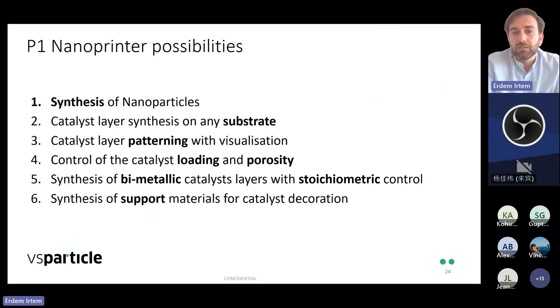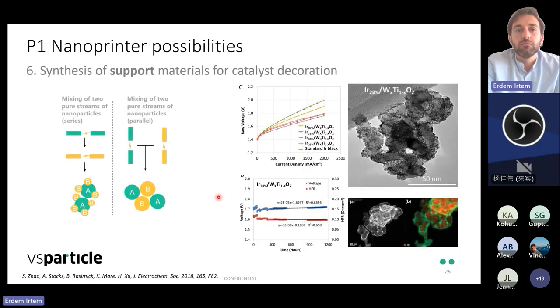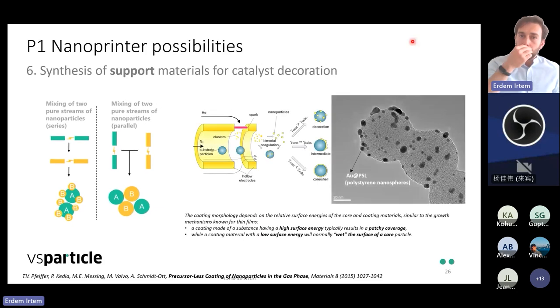So synthesis of support materials is also possible, which has been conducted before as well. Just to give you an example from PEM water electrolysis, I like this article from a few years ago where they have shown that tungsten doped titanium dioxide decorated with iridium was quite stable for over 1,000 hours. And when I was looking at the previous publications with the VSParticle generator, one of them, almost a decade ago, showed that it is possible to decorate, for example, gold on polystyrene nanospheres. That was just one application that was conducted. There are several others which are also possible in the literature. So there are techniques out there which could be employed to generate more different supported catalyst materials to decrease the iridium content, for example.